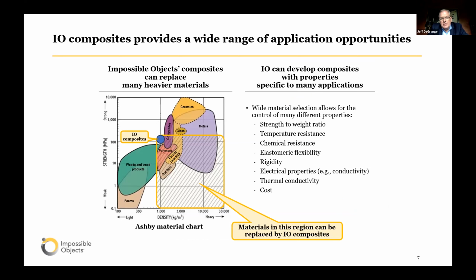So where does the Impossible Objects CBAM technology fit when you look at the typical material chart? This is your strength to weight density chart. That little blue circle in the center is where we're at today with material properties around the CBAM material combinations. What's interesting is that we have a similar strength to weight ratio as a 6061 aluminum, and we're about half the weight of a 6061 aluminum for those similar strength to weight ratios. So very beneficial if you're looking to have something of stronger properties and lighter weight.